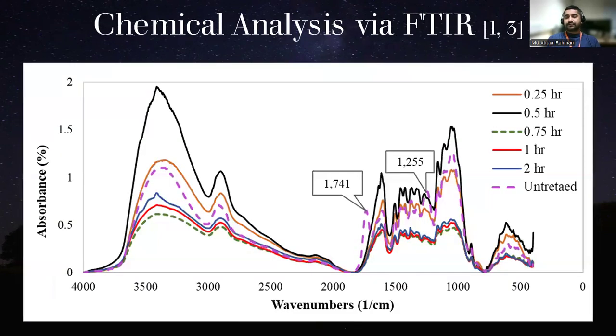Let's go to the chemical analysis. From the theory, we know that alkali treatment is also essential for the decomposition, or dissolving, of hemicellulose. Hemicellulose is not very good in terms of mechanical properties, because hemicellulose is hydrophilic. It absorbs moisture from the atmosphere, and that degrades the mechanical properties. So to confirm that, we did the chemical analysis through FTIR, and you can see that I distinctly marked two peaks. One is 1741, another one is 1255. These two peaks are a representation of the presence of hemicellulose.